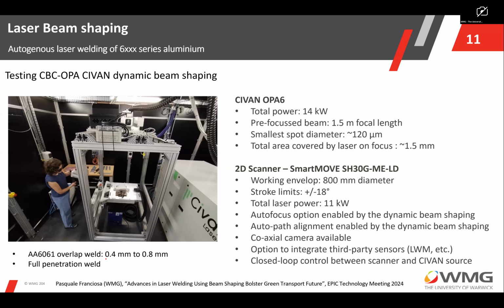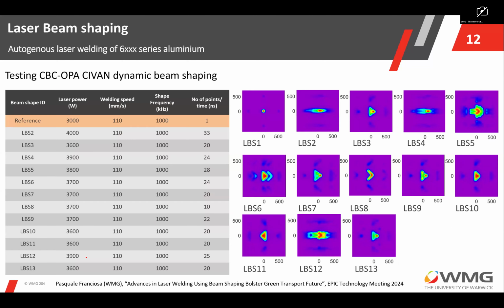So it's a combination of 0.4 to 0.8, 6061 aluminum in overlap. The requirement is a full penetration weld and obviously structural, so no major cracks. So we test a different shape. So this is one set, starting from a standard single core to something more like triangular or arrow-based shape.